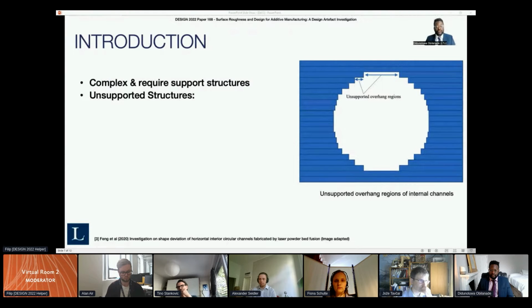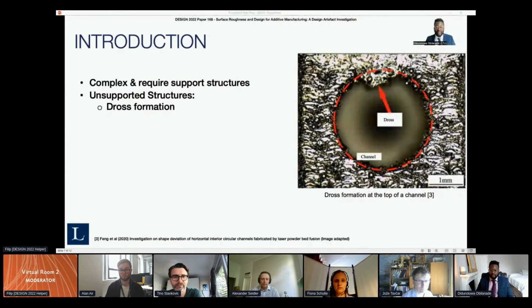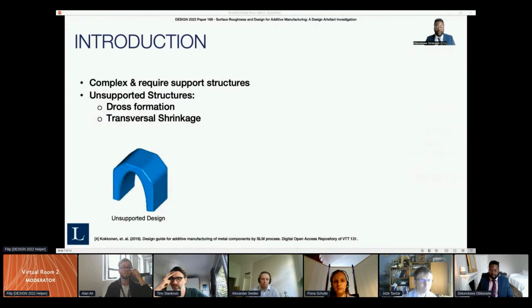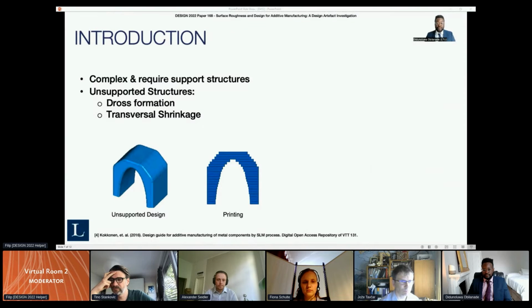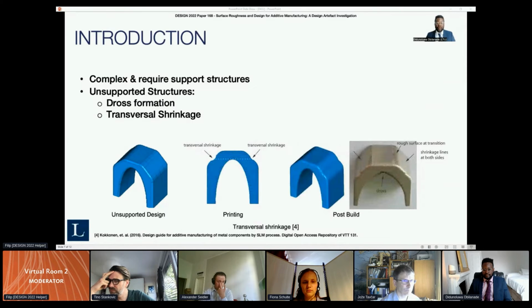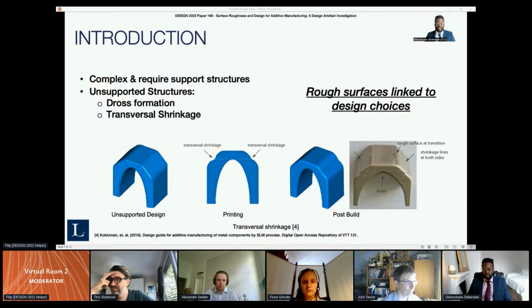However, for designs with closed internal sections, support cannot be included due to being impossible to remove post-build. These unsupported areas cause the melt pool to sink into the powder bed, and unsolidified powder leads to rough surfaces and dross formation, causing deviations from the part geometry. Additionally, without supports, transversal shrinkage occurs, as when 2 separately built islands meet, the residual stresses at their junction layer pull the material together, and like dross formation, cause rough surfaces and geometric deviations from the part design, hence intrinsically linking rough surfaces to design choices.